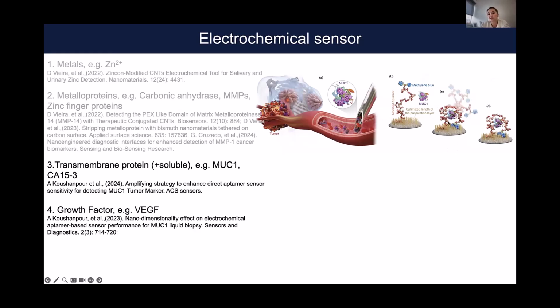And when it folds on itself, you can see that the redox probe here, the methylene blue, becomes very close to the electrode. And as you can imagine, when it comes very close to the electrode, it can transfer its electron. It can reduce and oxidize. So you can measure the signal. So basically, the signal you measure is going to be related to the concentration of mucin 1 in the electrode.